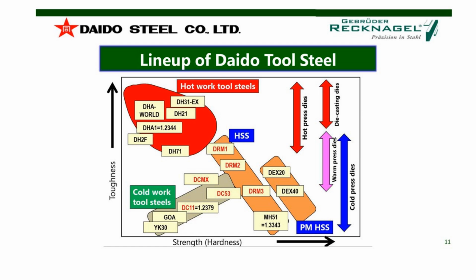The lineup of Daido steel grades for DCMX: you can see on the y-axis the toughness, on the x-axis the strength, and the positioning of D2 grade 1.2379 is in the middle of the gray area. Above there, you can find the positioning of DCMX. That means DCMX is running in the same strength range as D2 grade, with a hardness of 60 to 62 HRC, but the toughness is much higher than D2 grade. That's very important to know. Let's go forward.